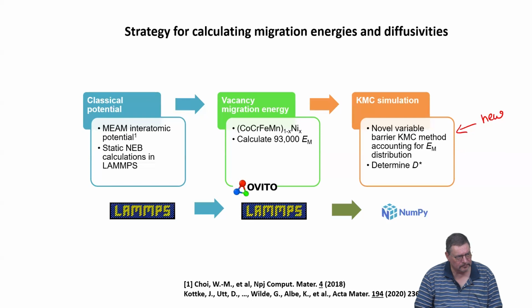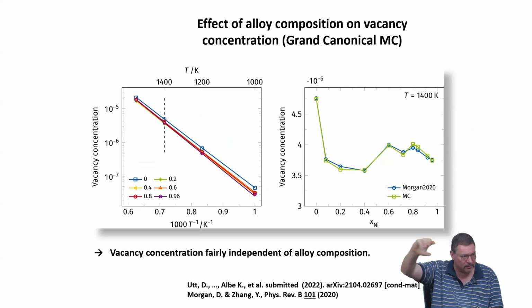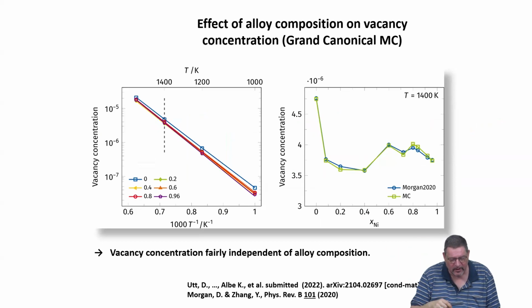Modified version of the Monte Carlo simulation. Yes, it's a further advancement, because normally you take an effective value for all of these atoms. And what they basically can look at, which we cannot do in detail in experiment, is, for example, vacancy concentrations as a function of the different alloy constituents. So they also went along the isopleth section, right? Pure nickel to Cantor. And these numbers here for the differently colored data are for the different alloy concentrations.